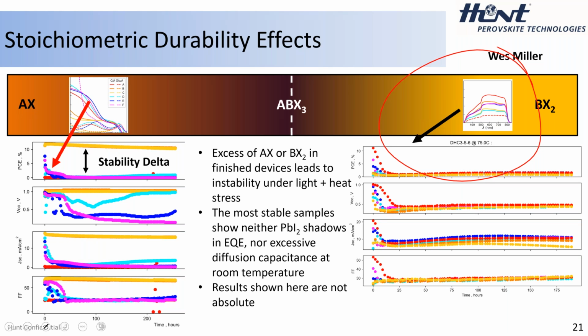that if you take our cells, and we're stressing these under light plus heat, so this is one sun light intensity at 75 degrees Celsius, persistent and concurrent. You can see these cells quickly decompose in around 25 hours. They just die right away. And we can see why here. So the spectral response of those same cells show a very strong lead iodide shadow.